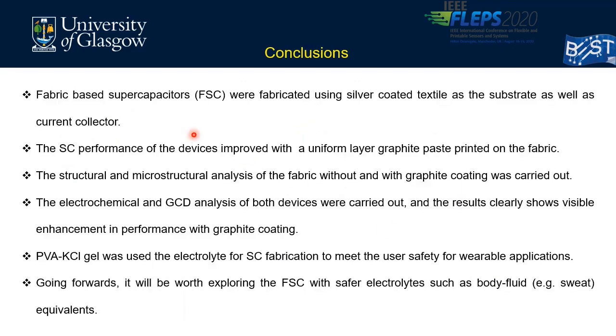In conclusion, we have fabricated a fabric-based supercapacitor using silver-coated textile as the substrate as well as the current collector. The supercapacitor performance of the device is improved with a uniform layer of graphite paste printed on the fabric. The structural and microstructural analysis of the fabric without and with the graphite coating was carried out. The electrochemical and GCD analyses were carried out. PVA gel was used as electrolyte for supercapacitor fabrication to meet user safety for wearable application. Going forward, it will be worth exploring the fabric supercapacitor with safer bioelectrolytes like body fluids such as sweat, etc.